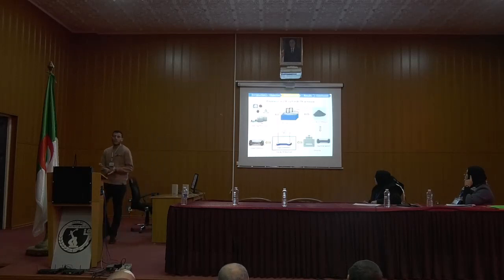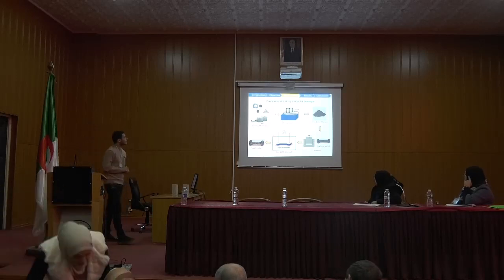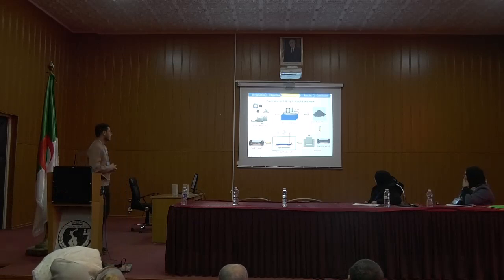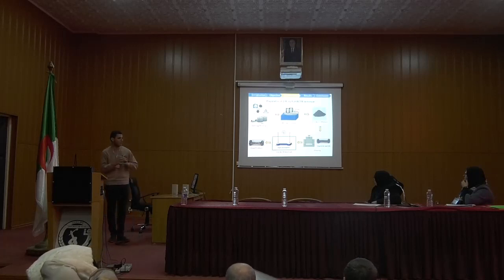So what is the preparation process of this material? First we start with a starting precursor, zirconium oxide, and we have boron carbide, and we have graphite. We introduce these raw materials in a jar for milling, for mixing. The next step is the mixing. We did a rapid mixing for around 15 minutes at a speed of 700 RPM. Then finally we get our mixture of raw material.